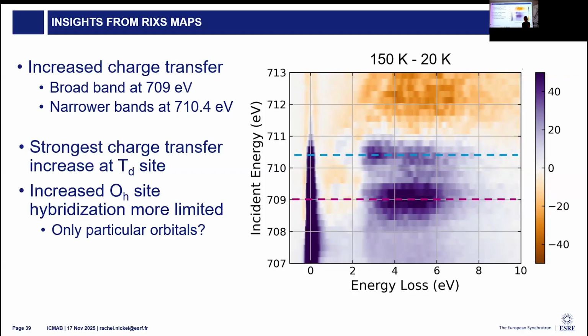So this is something that we're working on. Currently, there are no beamlines that have reported in operando measurements of soft RIXS. We have a couple of test experiments planned right now using solid electrolytes, where we're having promising results, and you can measure during the charging cycle. So the data I showed on the batteries were pre-charged and measured ex situ, but we have an in operando cell in progress. We have facilities on site if you have catalysis materials, where you can bring a reactor and then put it into vacuum.